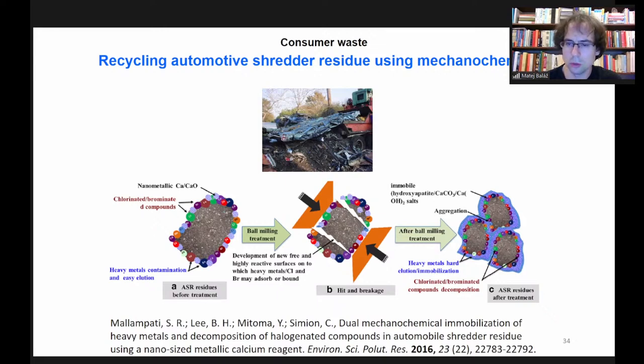This is also another big field in mechanochemistry, mechanochemical dehalogenation. So it's very efficient to use this procedure. In this case, there were two phenomena that were happening at once. And even this nanoscale calcium oxide was prepared by mechanochemistry. So the authors used the milling procedure two times.